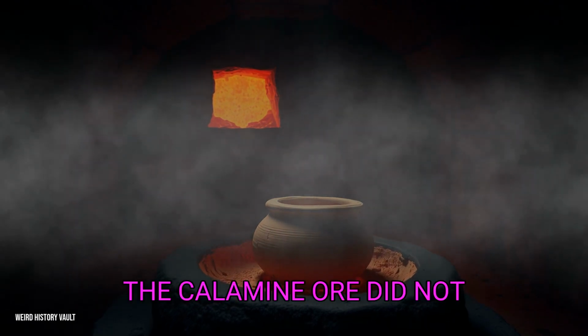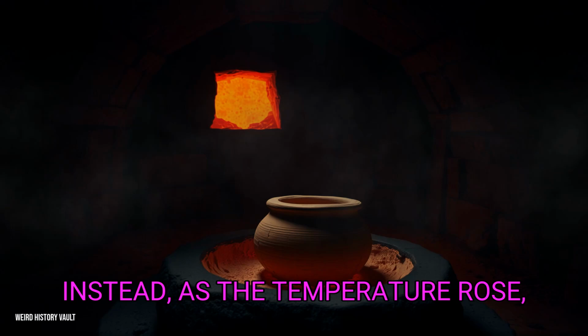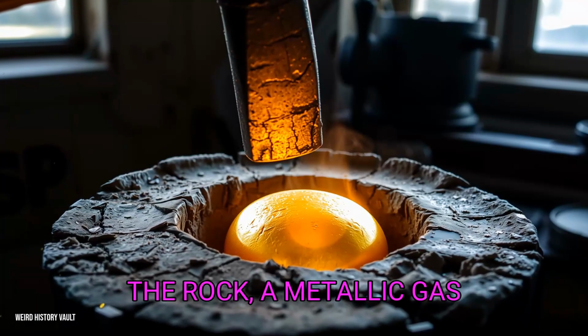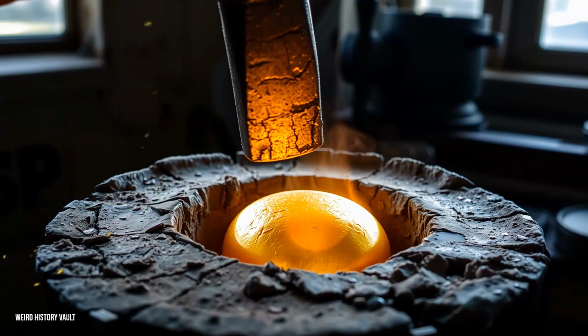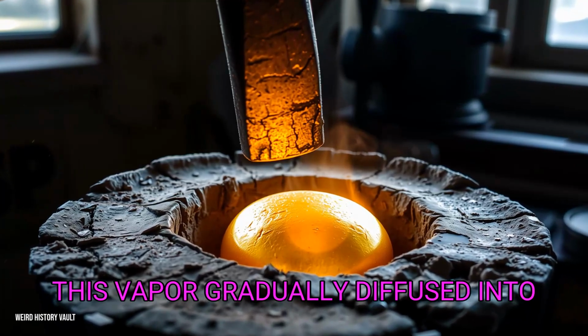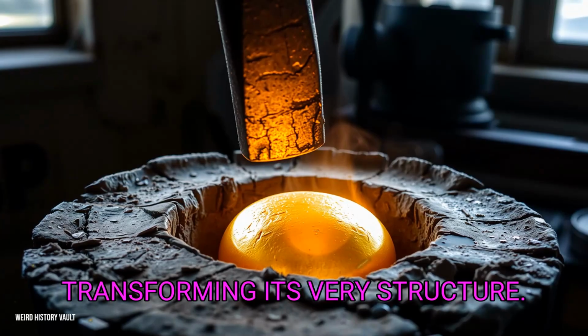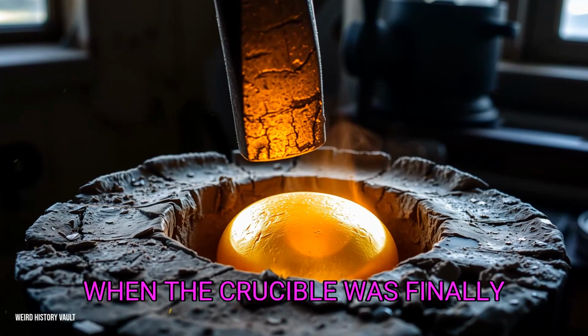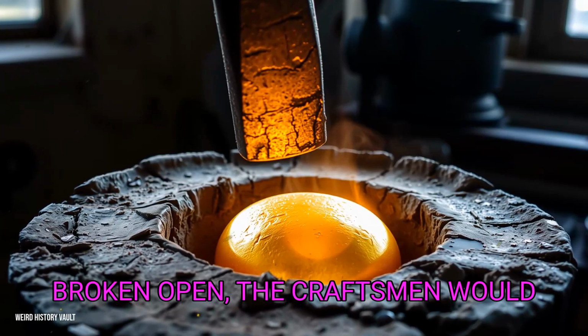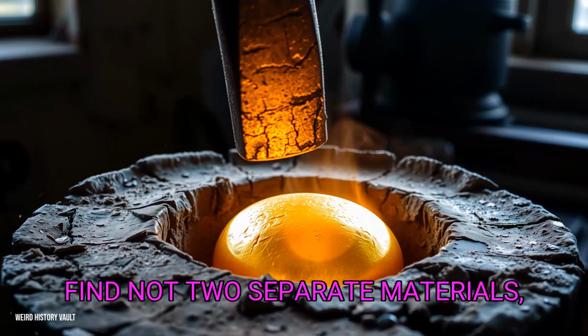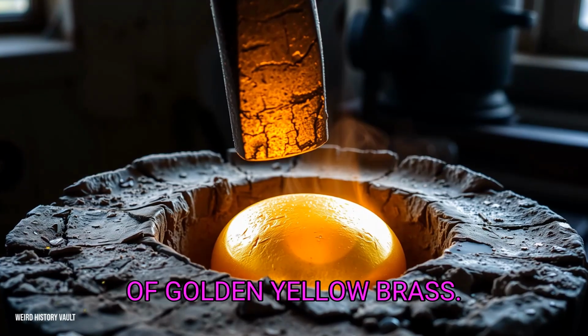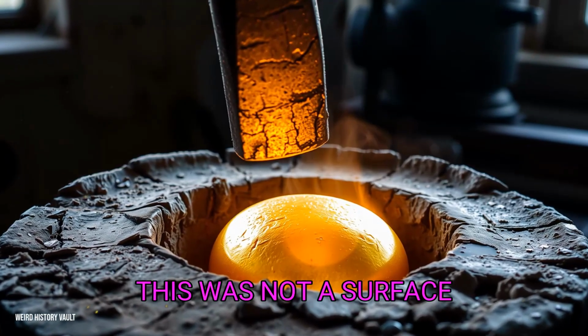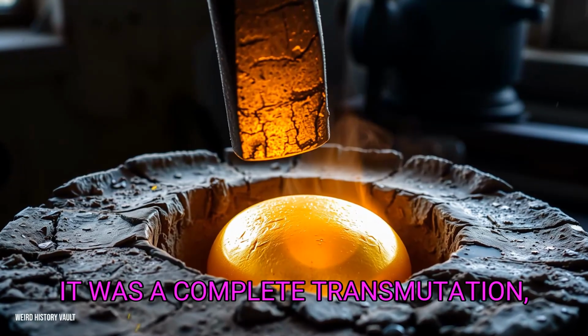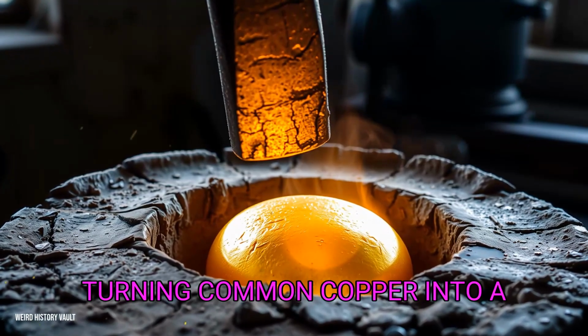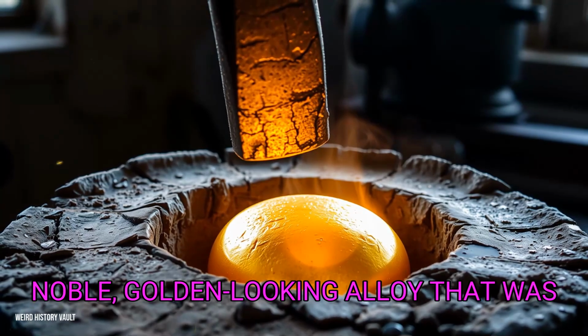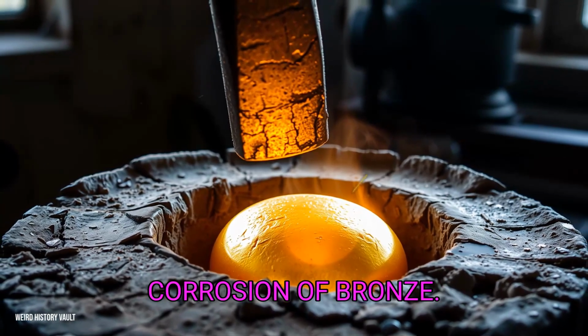The calamine ore did not melt. Instead, as the temperature rose, zinc vapor was released from the rock, a metallic gas that permeated the copper. This vapor gradually diffused into the copper, atom by atom, transforming its very structure. When the crucible was finally broken open, the craftsman would find not two separate materials, but a single, homogeneous ingot of golden yellow brass. This was not a surface coating, it was a complete transmutation, turning common copper into a noble, golden-looking alloy that was highly resistant to the green corrosion of bronze.